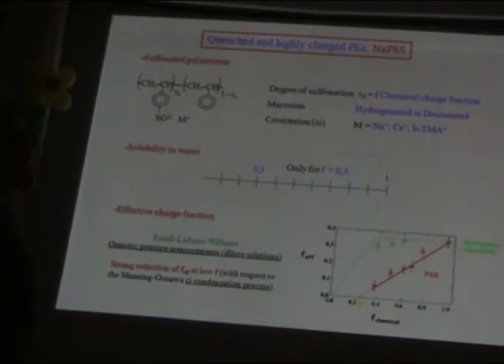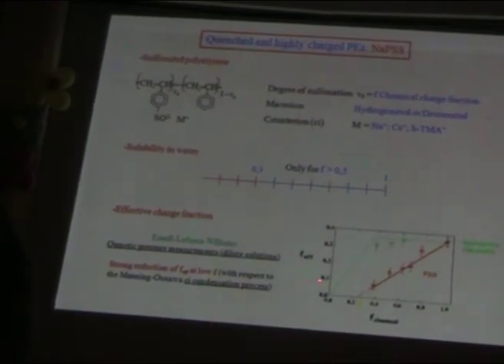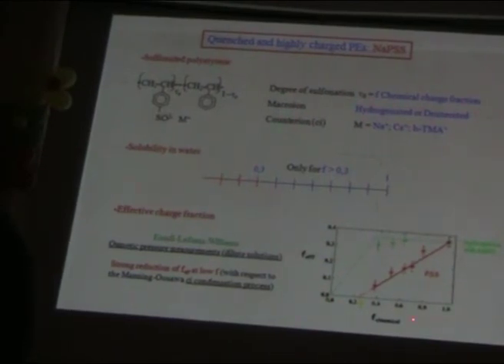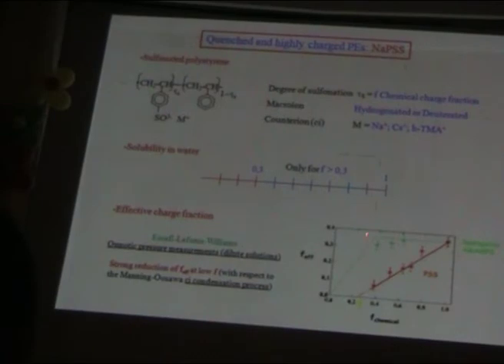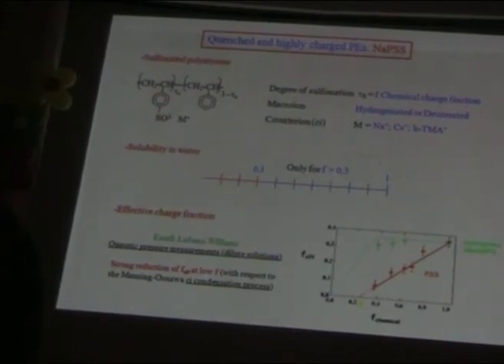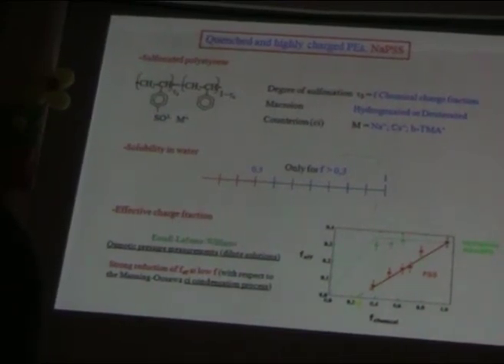Of course, here there is another point: it's a hydrophobic polyelectrolyte. Why? Because if you have a hydrophilic polyelectrolyte, when you increase the chemical charge fraction, you have an effective charge which is directly equal to the chemical fraction, until a certain threshold. Beyond this chemical fraction, due to the condensation of counterions on the macroion, the effective charge does not change.